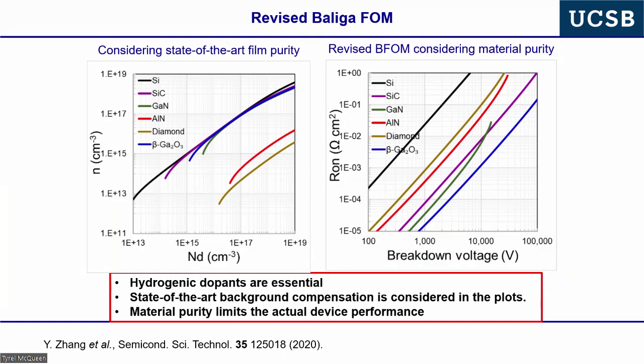And so what you find is that you can dope, that's fine, over a range. There's a lower threshold where you can actually dope effectively, and that's given by the stop points on these plots. And below that, you can't get controlled doping. That's just the reality of materials growth. This is where we fight very hard, okay? And then what you'll find is that for the materials with hydrogenic dopants, which are these, okay, you find almost a 1-to-1 correspondence between measured or predicted electron concentration and donor concentration.